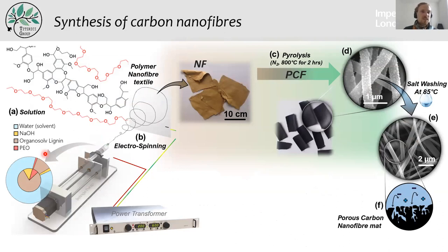So what we've been doing is solubilizing our lignin in an anionic solution with 0.5 molar concentration. We add a little bit of polyethylene oxide, and we use electrospinning to transform this solution into a nanofiber mat. Electrospinning is basically you put your solution into a syringe, you have a needle here, you put 20 kilovolts between this needle and an aluminium plate that serves as collector, and basically the solution gets pulled and transformed into nanofibers. These nanofibers are then placed into an oven under nitrogen gas at 800 degrees, and the sodium hydroxide starts activating the fibers, creating microporosity inside the fibers. And this one is very important for supercapacitors. And then you can wash away the remaining salt, the remaining NaOH, in a bath with hot water at 85 degrees.